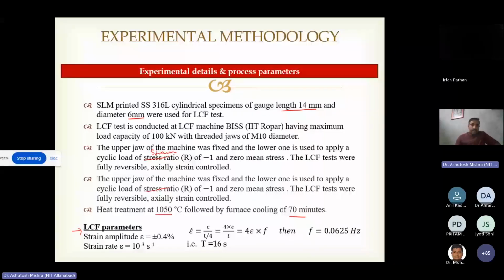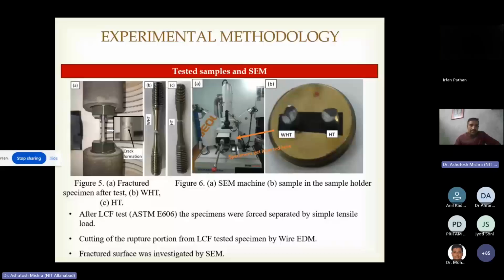Now, these are the tested samples. After the test, we can see there is a crack formation, highlighted here. WHT is for without heat treated and HT is for heat treated specimen. These are the samples of the fractured specimen. Then this is the SEM and the loading of the SEM sample for fractography.